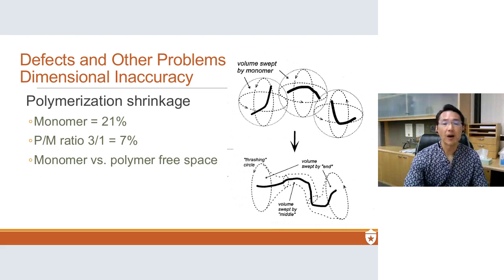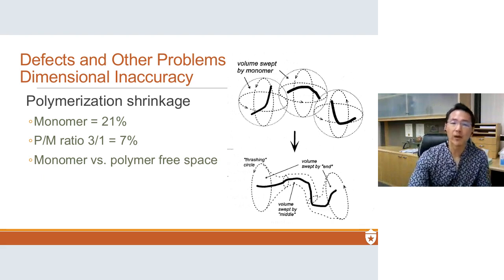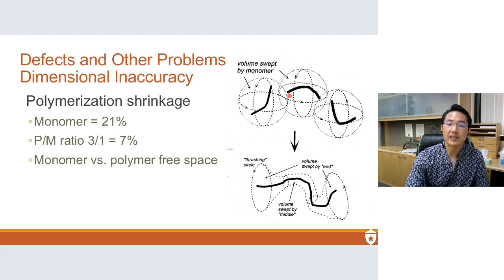Another major problem is dimensional inaccuracy, and there are several causes of that. First one is polymerization shrinkage. What happens is when you have monomer, it has its own free space. Now, when you start to polymerize it, you start to attach the ends of the monomers to each other, and you can see that it's now restrained. So the free space that it occupies is drastically reduced. And if you go from a monomer straight polymerized, you get 21% shrinkage.